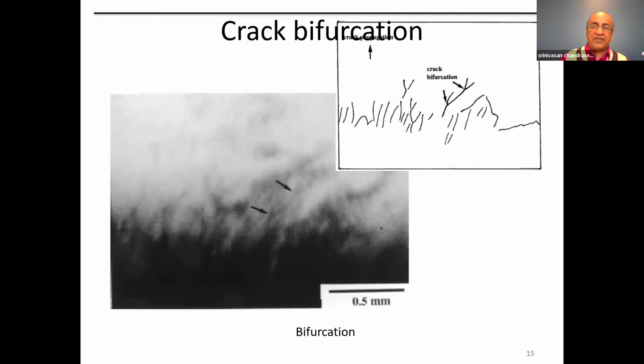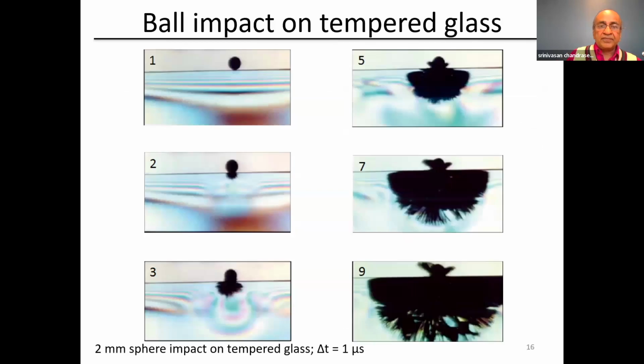So 2 things from these very high-speed images. One is the velocity of the crack always reached about 1,700 meters per second, which is roughly 40% of the velocity of sound in the glass, and that is usually a hard limit. And then you always have bifurcation of the crack occurring ahead of the front.